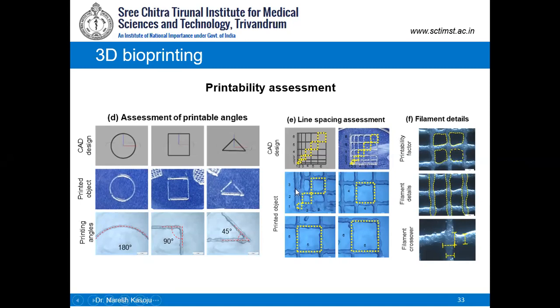But when it actually comes to print, here you give 1 mm of gap, but actually this 1 mm by 1 mm is totally collapsed. It just fused everything together. You don't see any gap as you see in the model. So this is a design which is a cascading, or incremental, gap, starting from 1 mm square, 2 mm square, 3 mm square, and so on, like a checkerboard type of design.